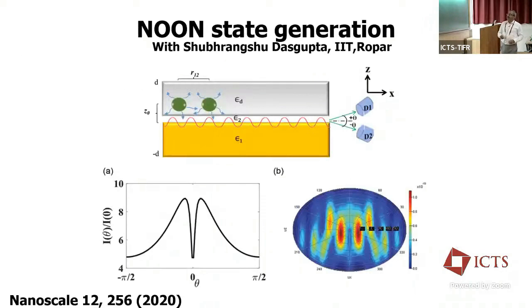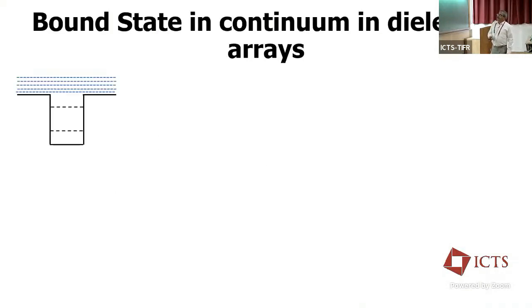Right. So we also proposed NOON state generation. This is again plasmon mediated. If you have two quantum dots which are embedded in a dielectric, and it is brought close to a metal surface, the emission from one of the quantum dots excites the plasmon mode, and that couples these two quantum dots together. And the emission from these, we showed, comes out in a NOON state. So both the photons will either be in detector 1 or in detector 2.